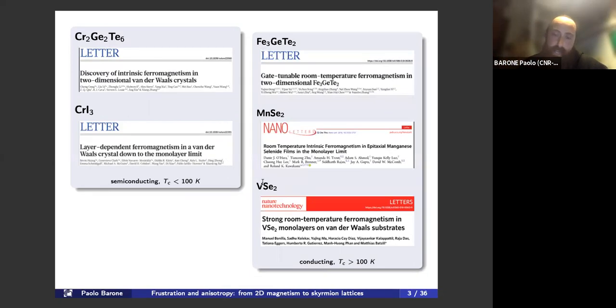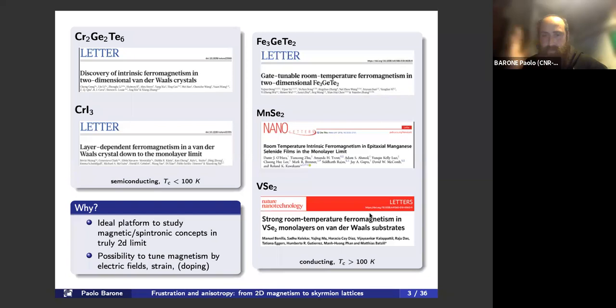These actually show some important differences with respect to these chromium-based systems, in the fact that all these materials are conducting systems, are metallic, so the magnetic properties are itinerant in character, and probably because of this, they have a much higher critical temperature that can also be easily tuned by electrostatic doping. And of course, the excitement about this system is, from my point of view, twofold.